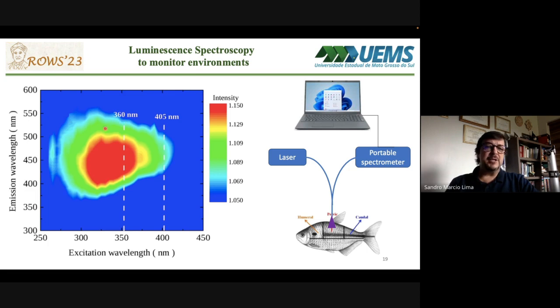In this excitation emission contour plot obtained for a fish scale, we see a broad band for excitation and a broad band of emission of the scale. It is known from literature that the main factors responsible for the observed fluorescence of fish scales are the fibrillary layers of collagen types and also the hydroxyapatite, the osseous part of the scale.